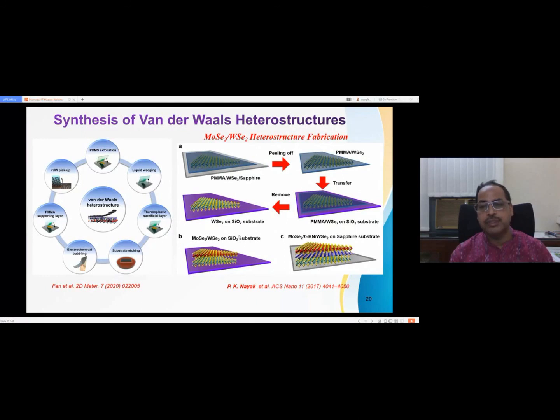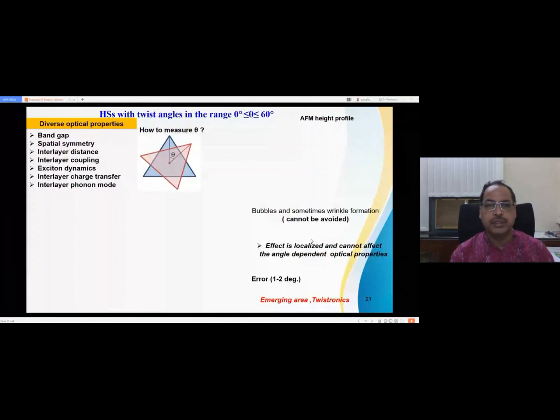For the heterostructure, I have two types of transfer technique. This is similar to the first process, but in the case of silicon oxide, I will take WSe2 on SiO2, then I will do the fishing. Then you can get the MoSe2, WSe2 on the SiO2. So you can see the two structures on the substrate. To see the interlayer coupling between the two layers, I included another hexagonal insulator between these two to avoid the interlayer coupling. So this is a three-step transfer process: MoSe2, WSe2, and this is the hBN layer. It is published in ACS Nano.